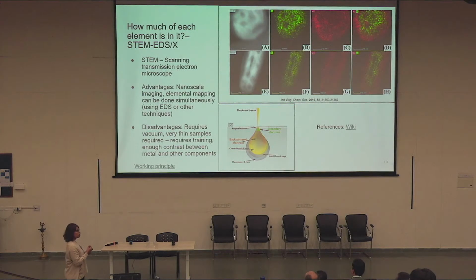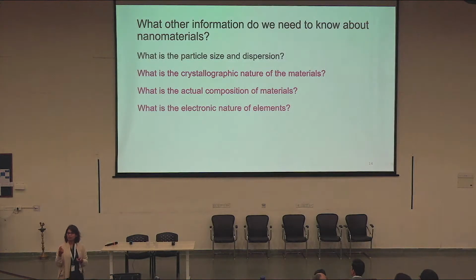But most of the time, when you have multiple elements present in your sample, you don't want to just know whether they are close enough to each other, but also, are they chemically interacting? In the sense, is there a charge transfer between these two elements? So let's say I have carbon and oxygen on my sample. It's not enough if carbon and oxygen are close to each other, right? I want a bond between the carbon and the oxygen. So if I want to prove that when multiple elements are present in my sample, there is actually an interaction between these elements, then I need to know the electronic nature of the element. That is, how much charge transfer is happening between 2 elements or 3 elements.